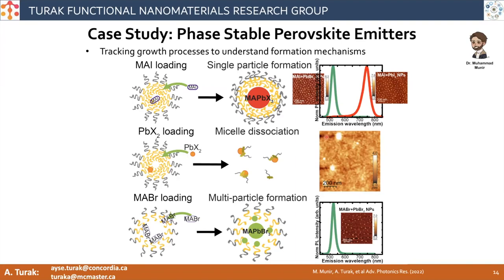Now, one example that I wanted to highlight about this control of synthesis was when you're making some of these metal organic halide perovskites. One of the big problems with these perovskites is their instability in a wide variety of aspects. But one in particular is if you have, for example, two components with two different halides and you mix them together, it's very difficult to maintain phase purity. They'll tend to very quickly react with each other and form an intermediate phase. So one of the nice things about our approach is that because we separate out different steps of loading, you physically separate the precursors, both physically and in time, so you have a little bit more control.